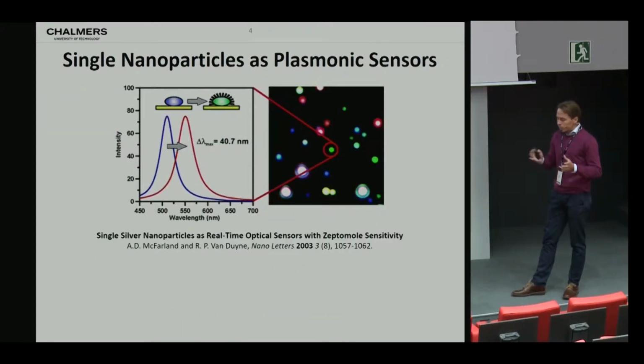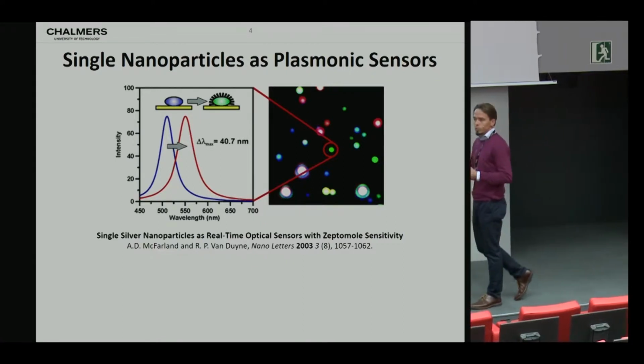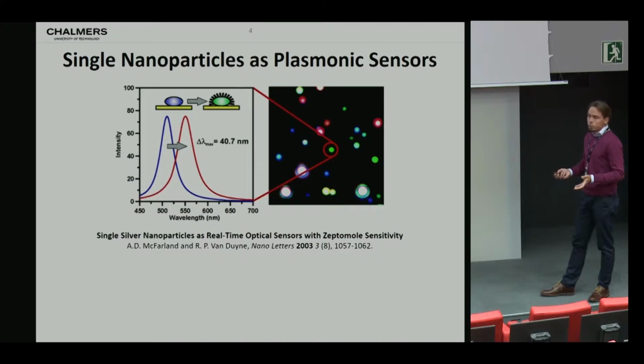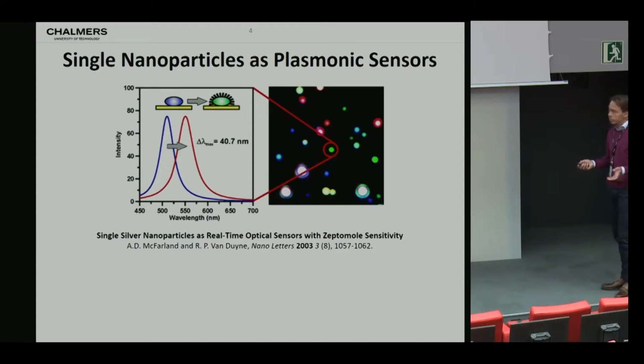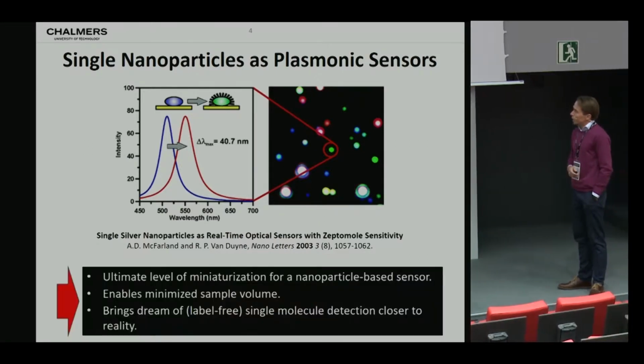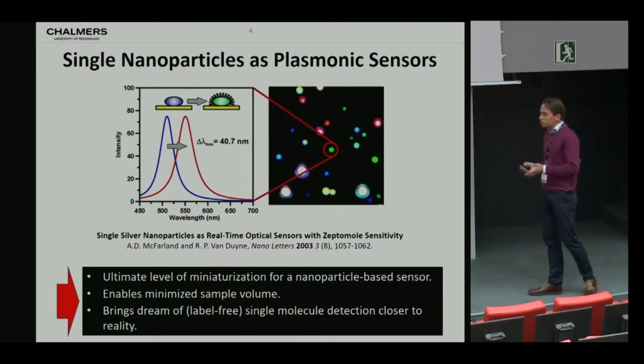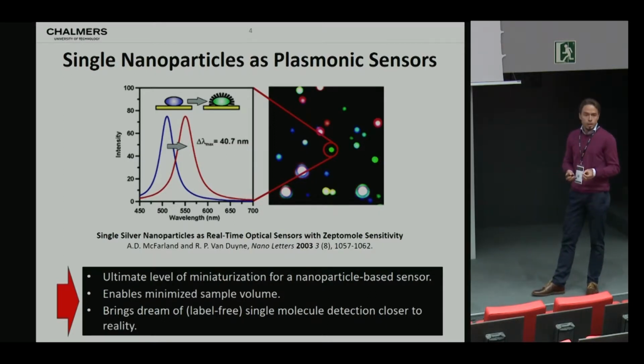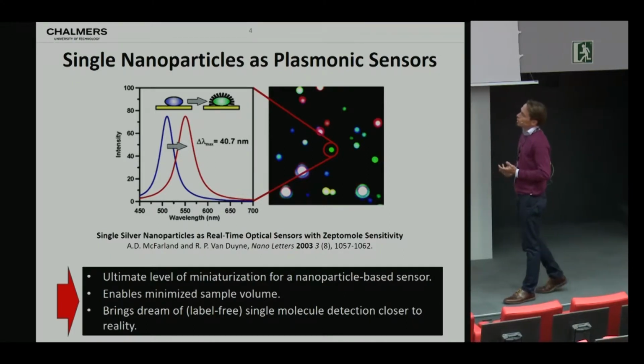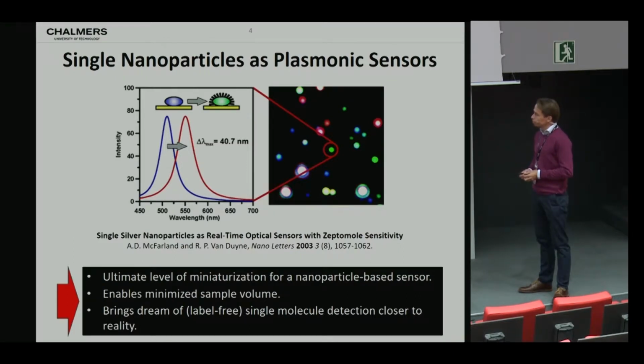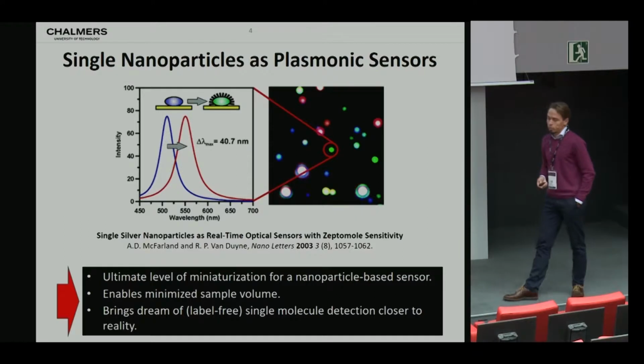Now, if we project that more into the field of nanophotonics and plasmonics, which is the topic of this conference, of course, people have tried and successfully used single nanoparticles as plasmonic sensors, as in this seminal work from the Van Duyne group from 2003. And why would you do this? Well, because it's the ultimate level of miniaturization for a nanoparticle-based sensor. You cannot make it any smaller than using one nanoparticle if the nanoparticle is your sensor. You really minimize the sample volume that you need to create a signal, and it brings the dream, which is now maybe no longer a dream really, of label-free single molecule detection closer to reality.